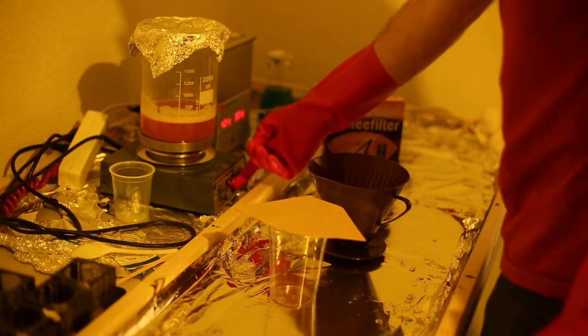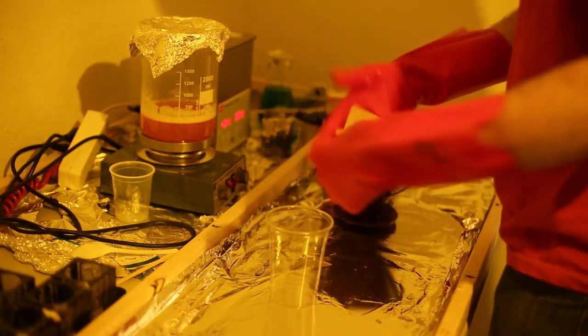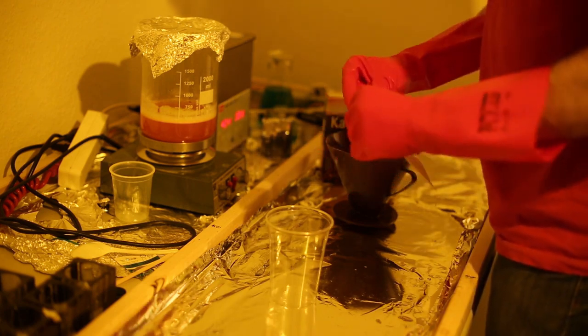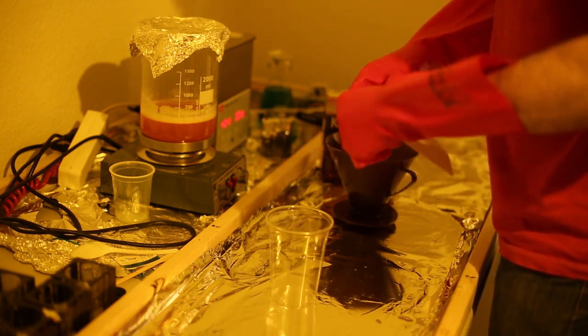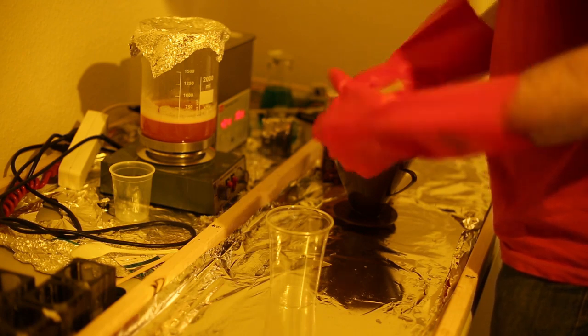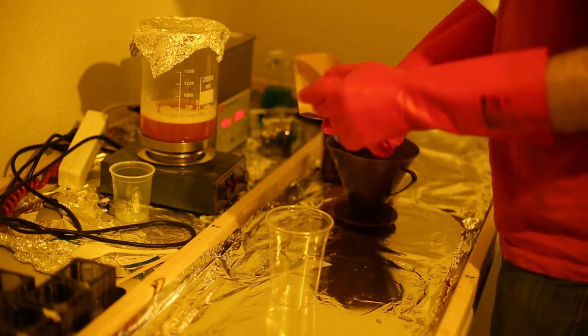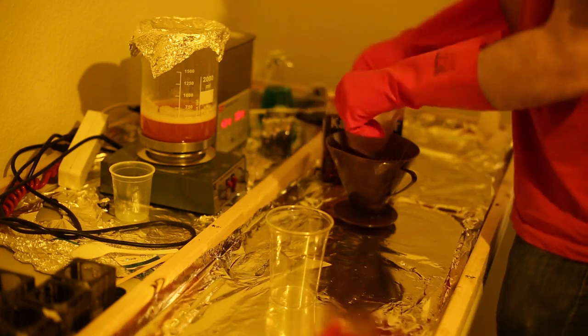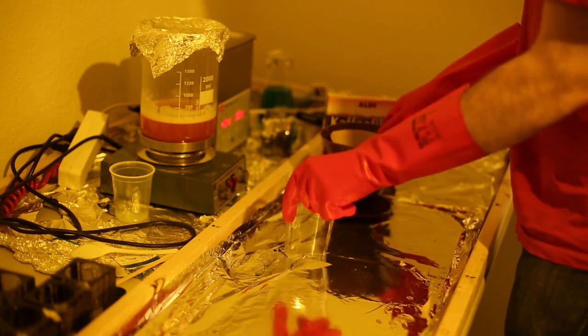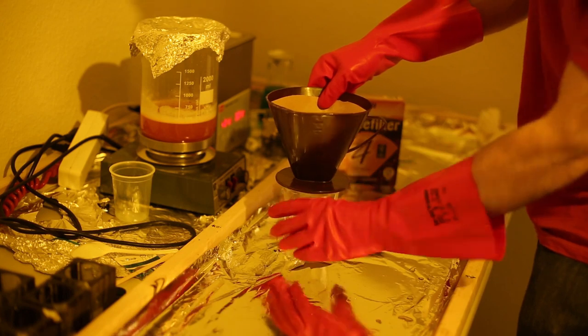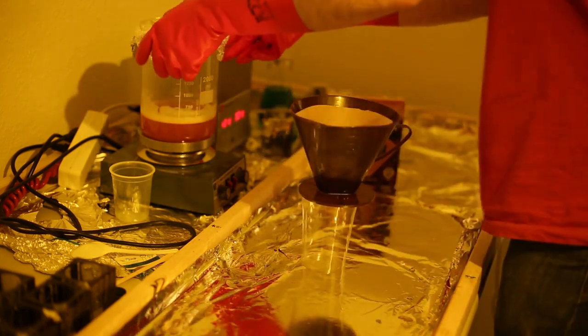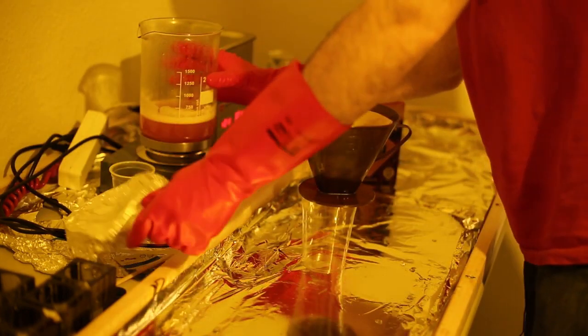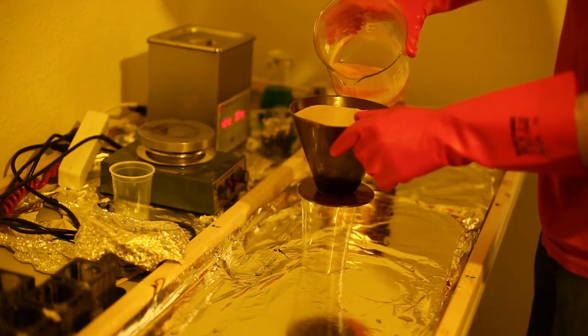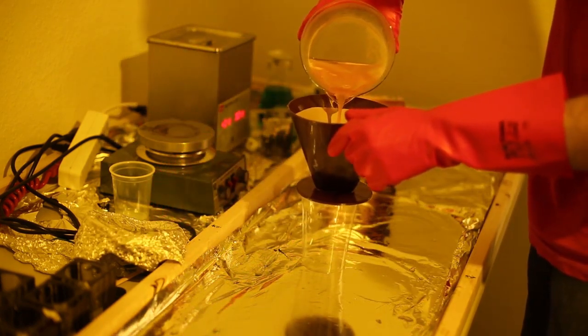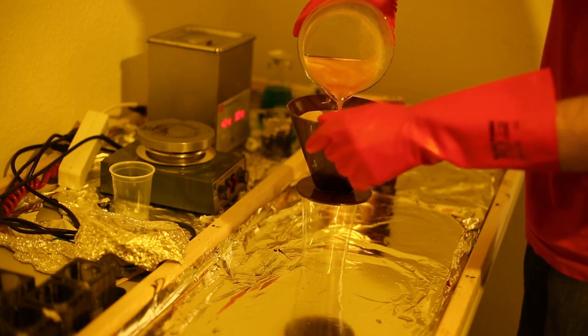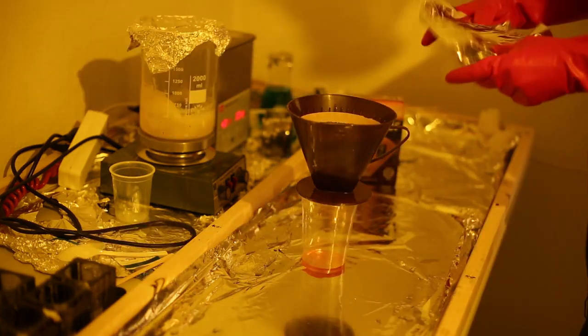For that I use the cheapest Aldi coffee filters. I've tried the more expensive filters as well, but they tend to rip and don't yield better results. It takes about 15 minutes for the gelatin to pass through the filter and flow into the transparent cup at the bottom. While the gelatin is inside the filter holder, it tends to cool down very quickly, making it harder to penetrate the filter. So for thermal insulation, I put a tinfoil cover on top of the holder.